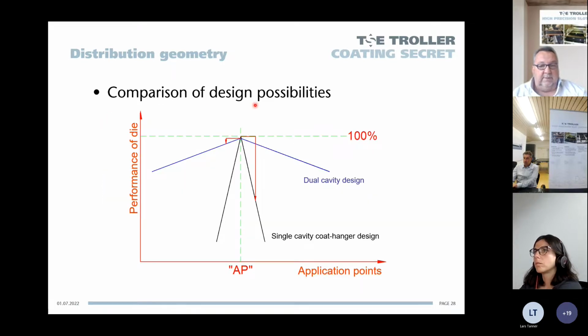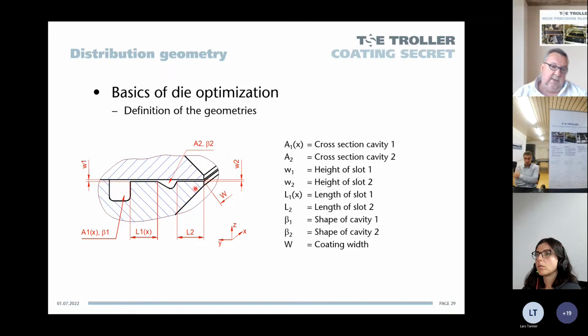When you compare the different possibilities here, single cavity coat hanger and the dual cavity, we have in the diagram here the different application points. This is the, say, design condition there, and performance of the die means how close are we at a perfect uniformity in crossweb direction. With the single cavity, we are really up to the 100%. But if you move away a little bit from that optimum point here, the performance is dropping significantly. And with a dual cavity design, it's much more robust, and we can really achieve a good uniformity for a lot of different products on the same die. Here you see how the distribution system looks like. We have in total maybe about 13, 14 parameters which we define for the dies, especially for production dies.